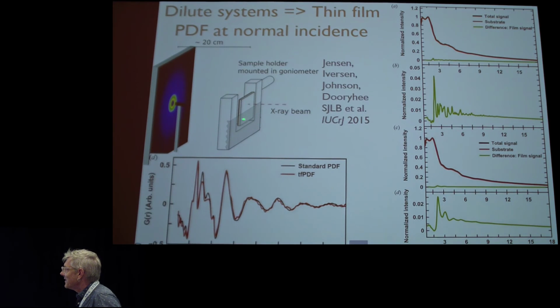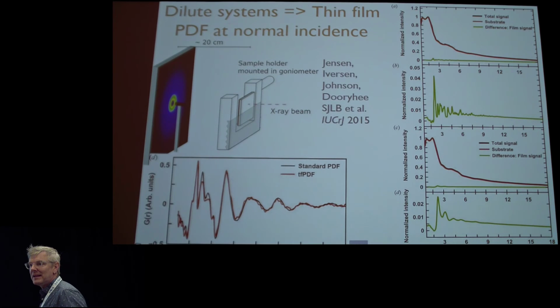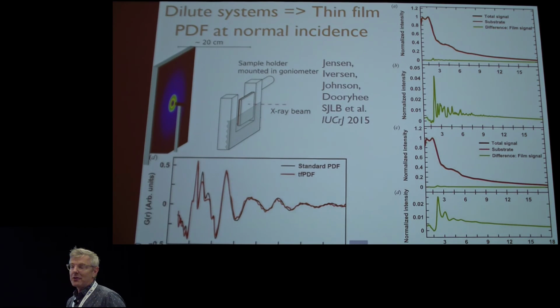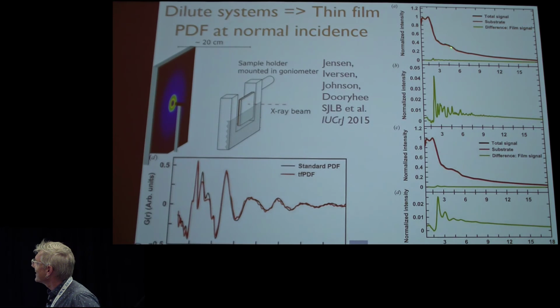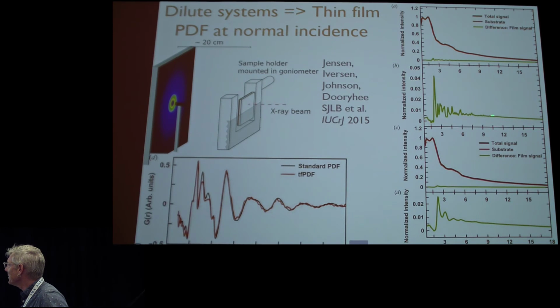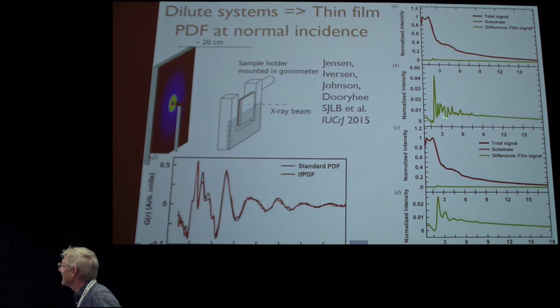Because we can measure these very small signals, we figured out that we could actually do thin film PDF in normal incidence. So what we do here is we have a substrate, and the material of interest is a film. And there's two PDFs here. The red one is just the substrate, and the black one is the substrate with the film on it. And there's a tiny little difference curve. And we blow up the difference curve. We have good signal to noise, good reproducibility, and we can actually get the structure out.